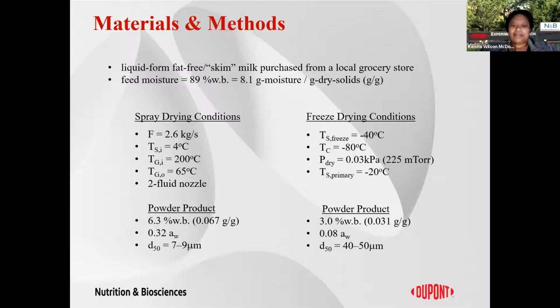You see the conditions here that were listed for the spray drying and freeze drying processes. And then finally, you see that the product collected for spray drying, the spray dry powder was about 6% moisture, whereas the freeze dry powder was about 3%. You see the water activity, it was about 4x for the spray dry powder. It's more moisture content and higher water activity. We talked about the relationship between the two already, but you see a little bit lower water activity for the freeze dry powder. And then there's analysis of the particles that were produced.